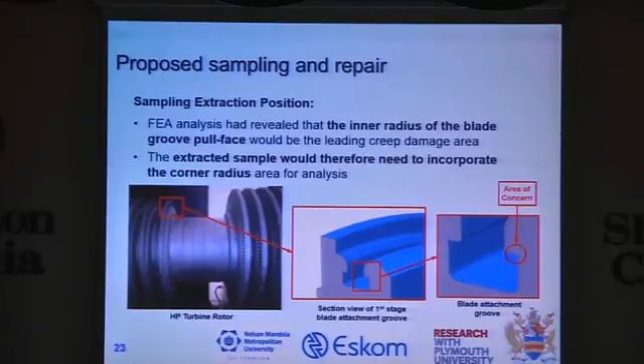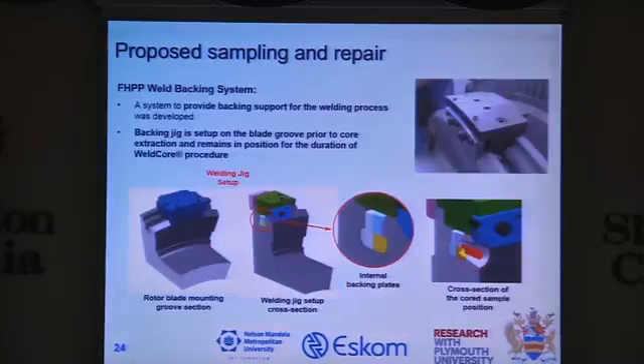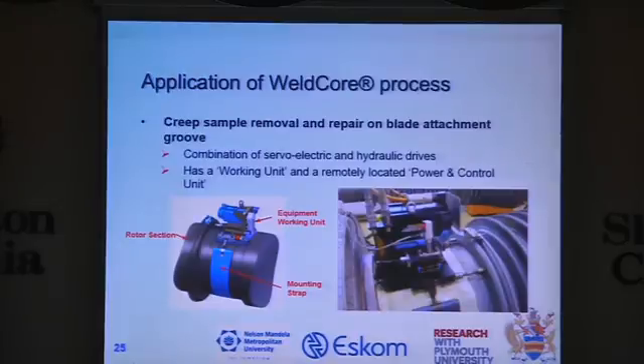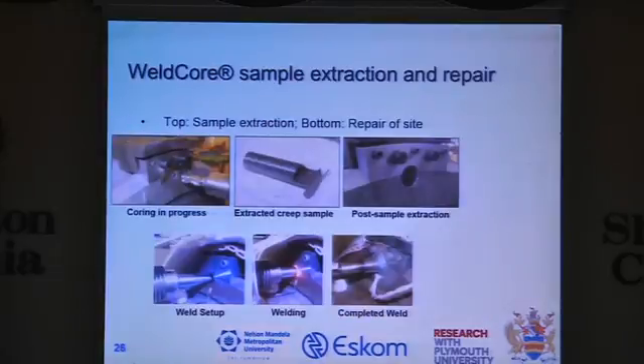So what we've done is develop a process whereby we are confident with our friction hydropillar repair process. We now need to convince the people that we can take a sample out and repair it safely. If you look at what we've done here, we've developed some backing inserts that go into the T-slot there, and that little red piece of material sitting there. Because it's a through hole here and we need backing for our process, we have to put backing in. All of that is sacrificial, and can be machined away afterwards. Develop your platform, put it in place, and not much more.